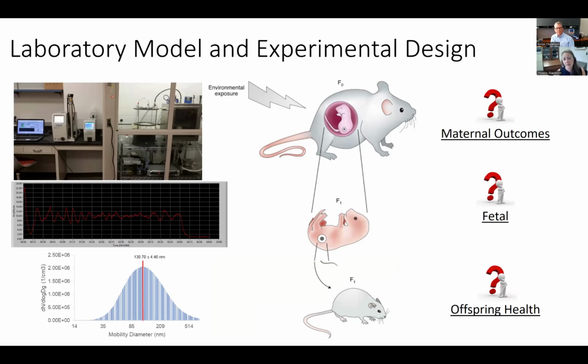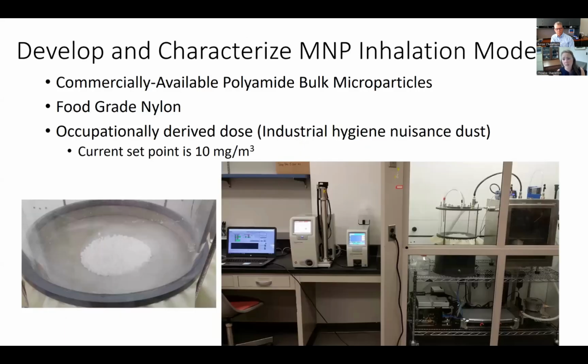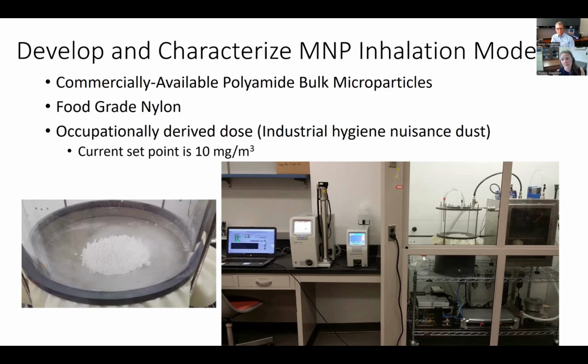So in this case, we developed a micronanoplastic inhalation technique and methodology. We purchased commercially available polyamide, a nylon particle, bulk microplastics. It's a food grade nylon at that. And we have a set point of 10 milligrams per meter cubed, which is an industrial hygiene nuisance dust dosage, but it's an occupationally relevant dose at the same time.